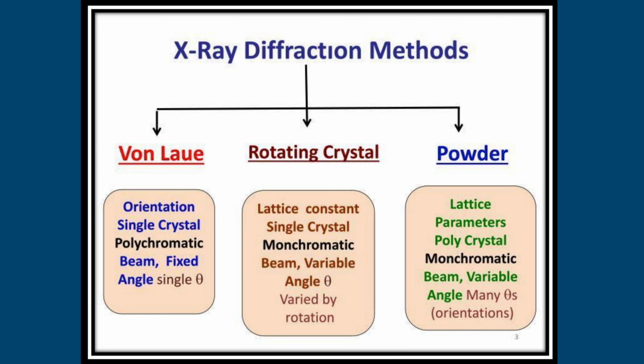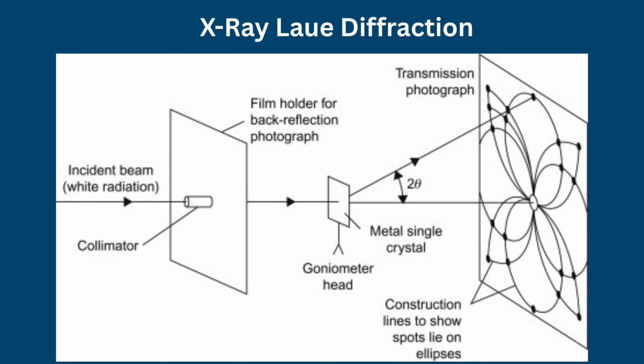When the diffraction conditions of a crystal are unknown, two classical approaches are commonly employed: the Laue method and the rotation method. The Laue method uses a stationary single crystal exposed to a polychromatic or white X-ray beam. Because the crystal simultaneously diffracts multiple wavelengths in different directions, the method rapidly provides information about crystal symmetry and orientation. However, overlapping diffraction spots often complicate interpretation, particularly for complex structures. Consequently, the technique is mainly used for qualitative crystallographic analysis.